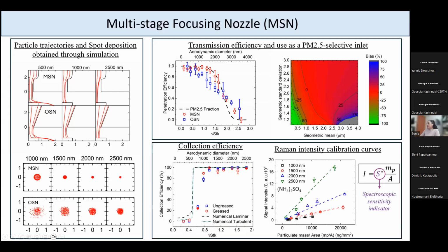Here is the collection efficiency that I saw experimentally for the multi-stage focusing nozzle in comparison to the numerical simulation, which is a relatively good match. And finally, I got the Raman intensity as a function of the mass density collected on the substrate. When I used the multi-stage nozzle, I got 4 different calibration curves for 4 different particle sizes because unfortunately Raman intensity depends on the particle size.